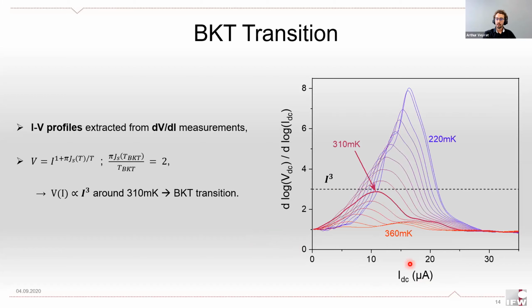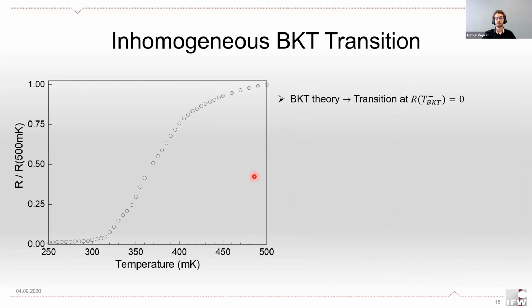These IV curves are obviously obtained by applying a DC current, so these measurements are made out of equilibrium. Maybe to have a better proof of having a BKT transition, we can look at equilibrium measurements. So this proof is from looking at the resistance versus temperature profile once again. According to the BKT theory, we expect to have an abrupt transition to zero resistance below the BKT temperature.